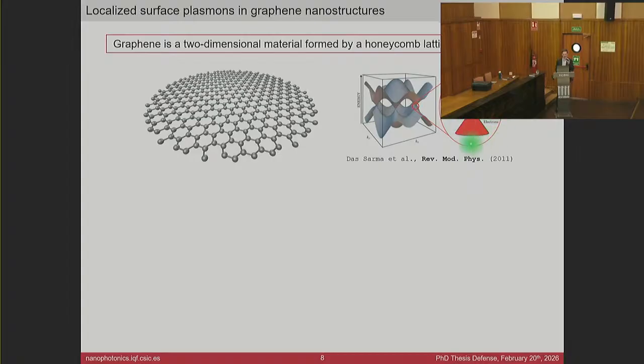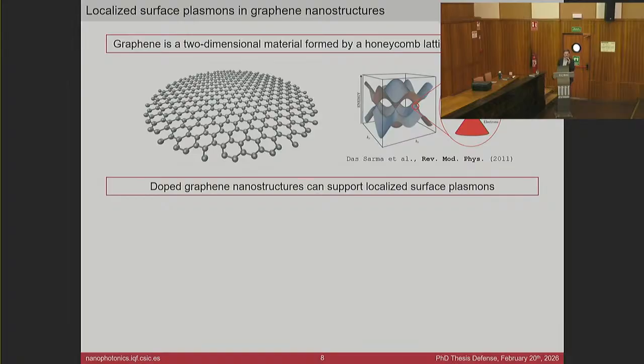We see that we have a completely filled valence band, an empty conduction band, and we have a zero band gap. So in principle, we don't have electrons in the conduction band, and it couldn't, for example, sustain localized surface plasmons. But if we dope it, if we add electrons to the conduction band, then graphene becomes conductive, and it can sustain localized surface plasmons. So let's see how we can do that.